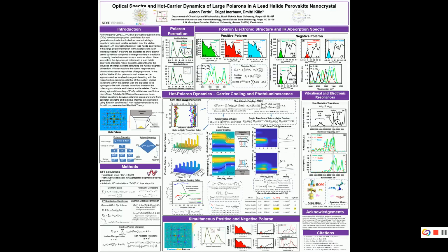The most pressing thing is that for material considerations, we deal with lead orbitals, lead p orbitals, and those have high angular momentum. So we have to include spin-orbit coupling in the calculation. And then it took some work to extend that to our non-radiative dynamics. So that's one of the methodological novelties of this work.